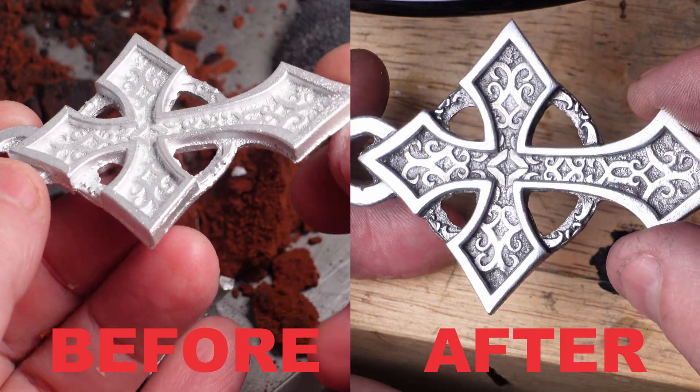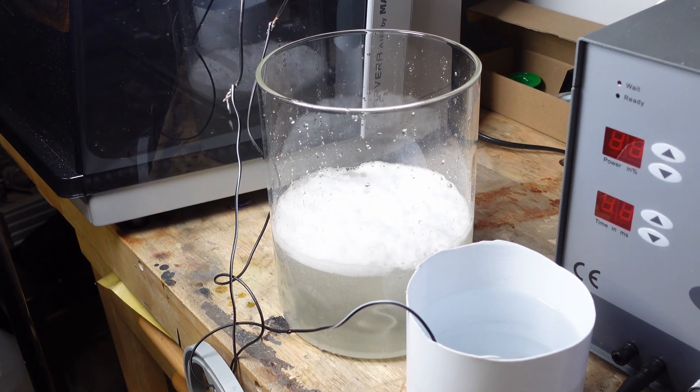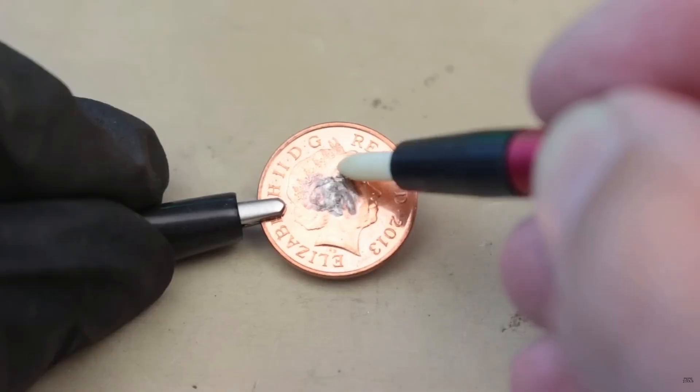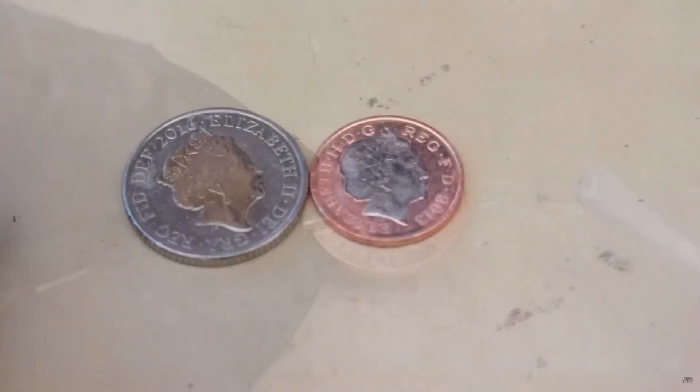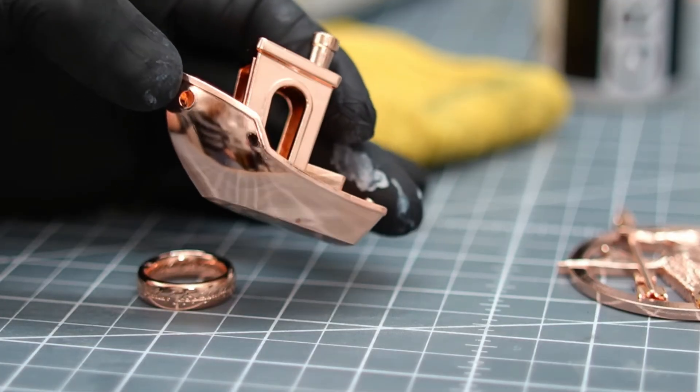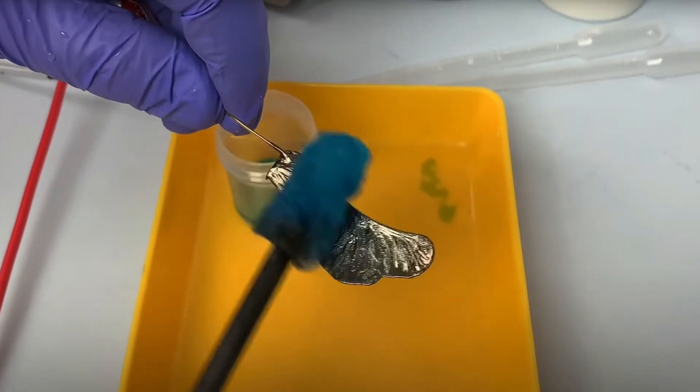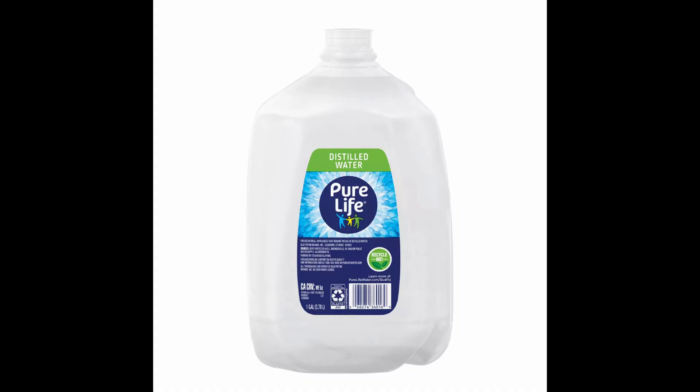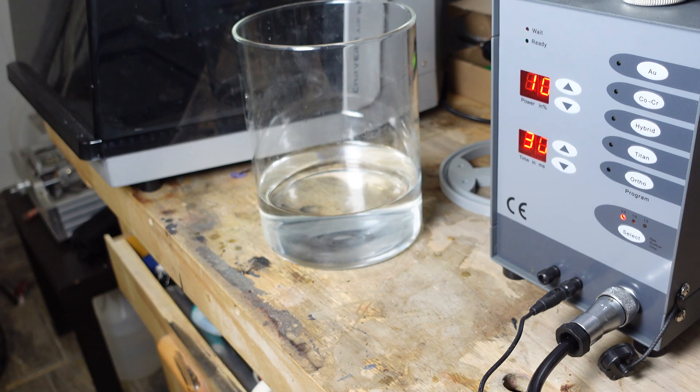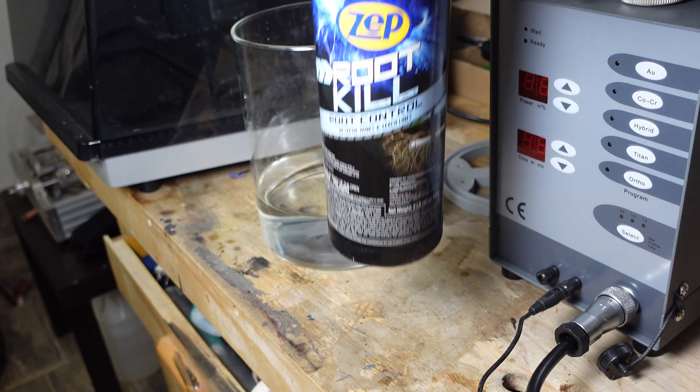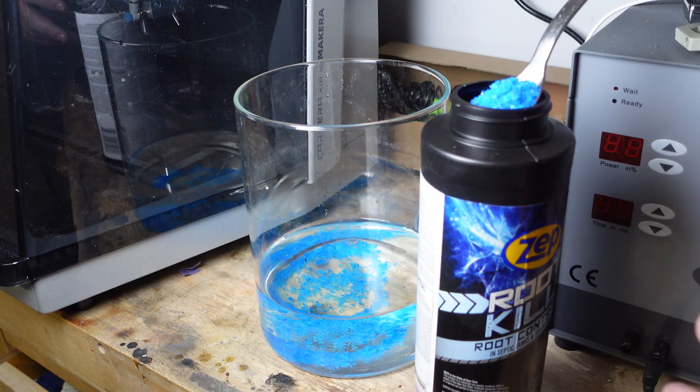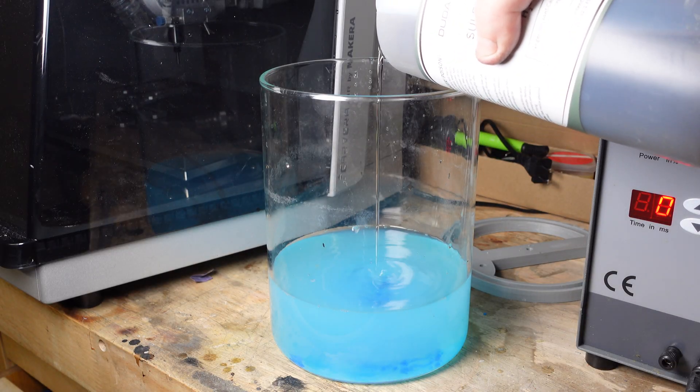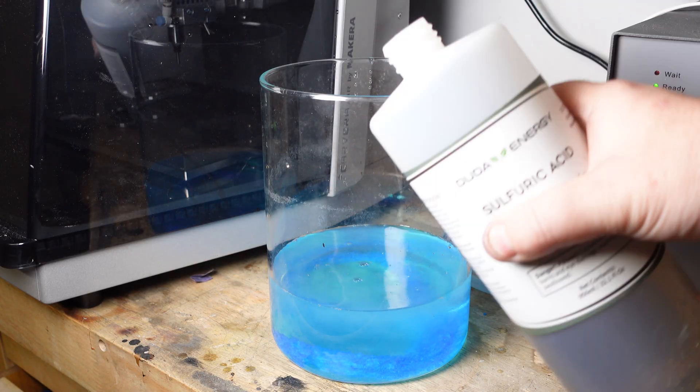Now I want to try plating. Let's see if the machine can do that. I think plating would be much more useful if it works. We can potentially do immersion plating, brush plating, electroforming - which is really cool, it lets you not only coat 3D printed objects with metal but you can even coat organic stuff. It's a cool process. For this the electrolyte is a little different. We're going to start with water - you should use distilled water but I didn't have any, and since again this is just a proof of concept I'm using regular bottled water. For my copper I'm using root killer that you can get from Home Depot, which is pure copper sulfate, and we finish with about five percent sulfuric acid. You should always wear gloves when handling acid, but I can't operate the camera with gloves so I'm winging it. But this is really stupid, you should be smarter. When the copper sulfate fully dissolves you're ready to go.